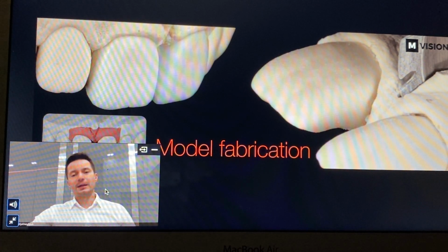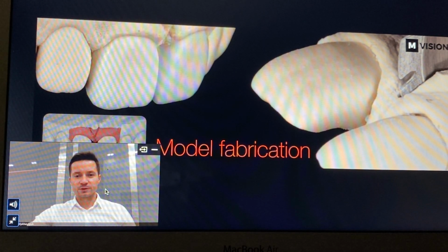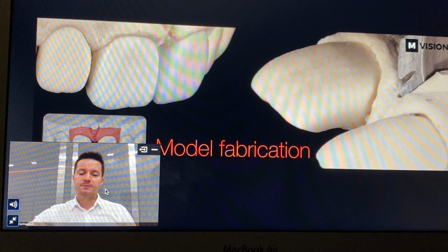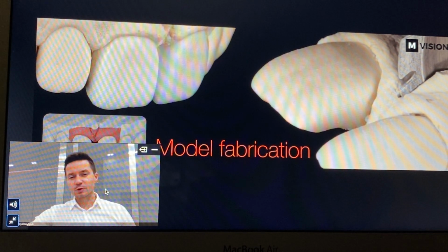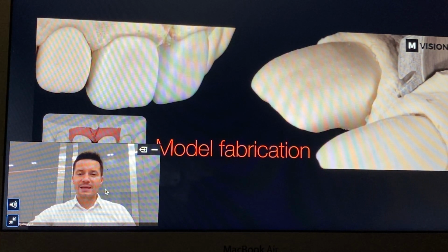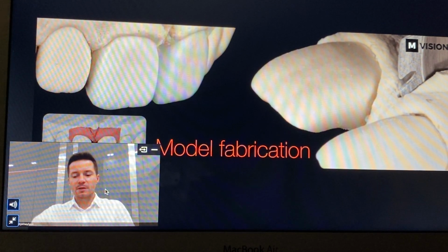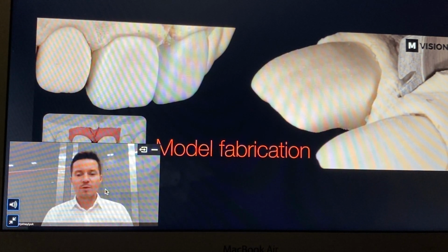Usually when we speak about the analog workflow and ultra thin restorations and the high level restorations, we mean feldspathic restoration. But when we speak about feldspathic restorations, we also have two ways how we can create them. The way number one is layering on platinum foil, so platinum foil technique, and the way number two is actually layering on the refractory material. And in this specific case, because we need the ultra thin veneers plus as fast as possible, we decided to use the platinum foil technique.